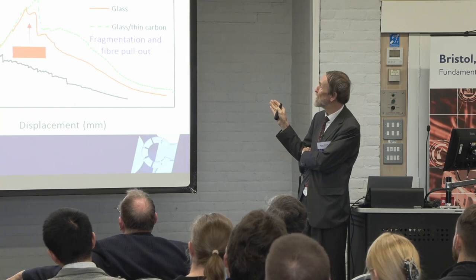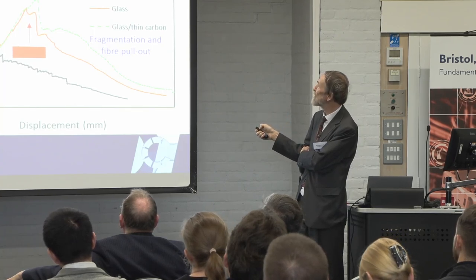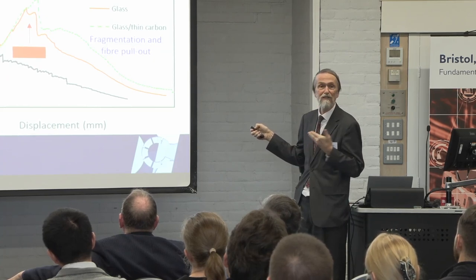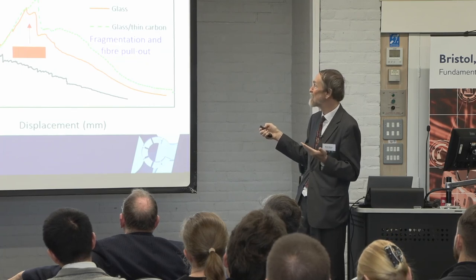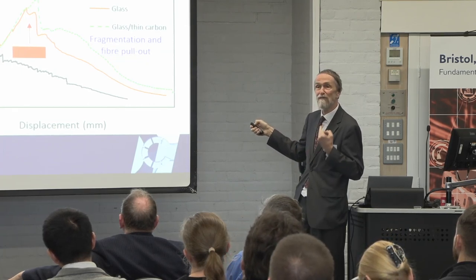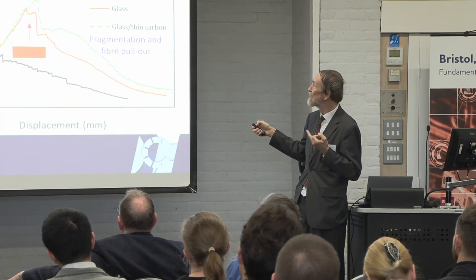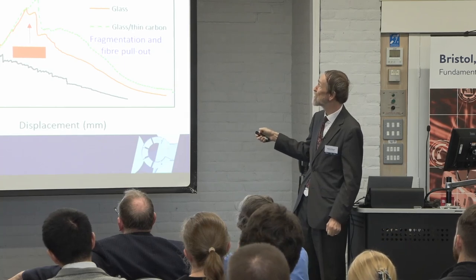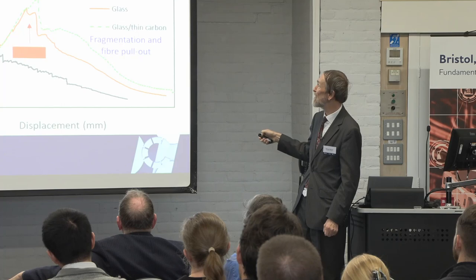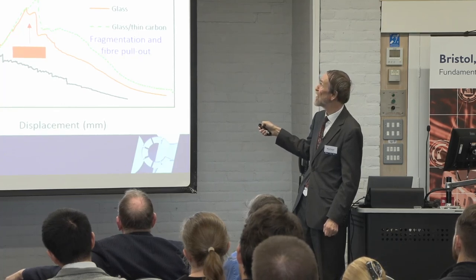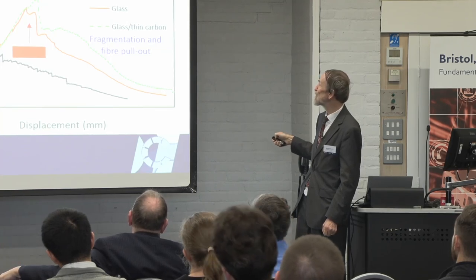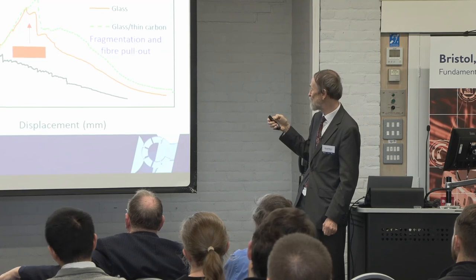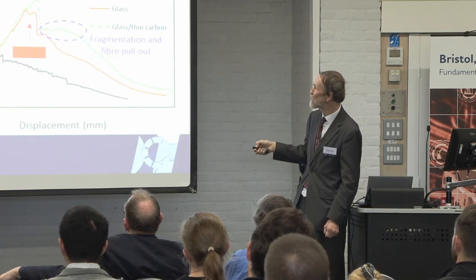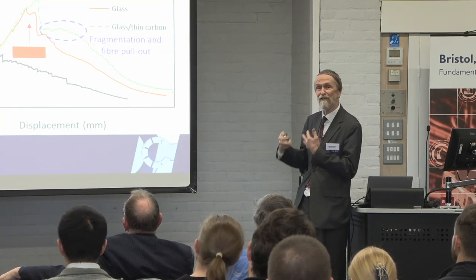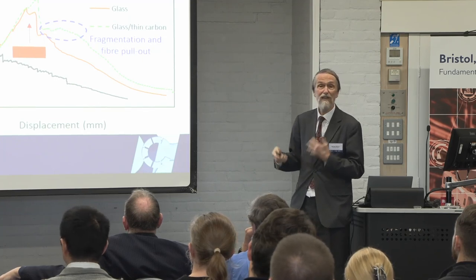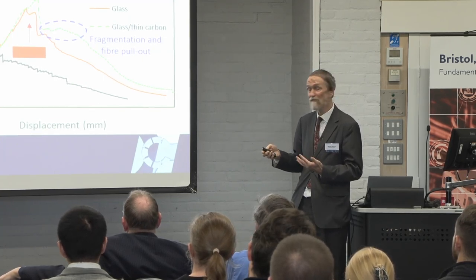And the final one I want to show here is where we look at introducing some thin carbon between the glass in order to introduce some of this fragmentation behavior, which we saw in the pseudoductile tensile mode. So by having this on the back face, what we want is to improve the energy absorption in tension on the back face. And you can see that this improves quite significantly over and above what we get with the glass. It both actually increases the load here because of the hybridization of the carbon, and then it gives us this much longer plateau area here, where what we're getting at that point there is the fragmentation. So we're getting fragmentation in the carbon because of the thin carbon in the glass. That fragmentation absorbs more energy and gives us an improved energy performance and ability to deal with penetration under impact conditions.